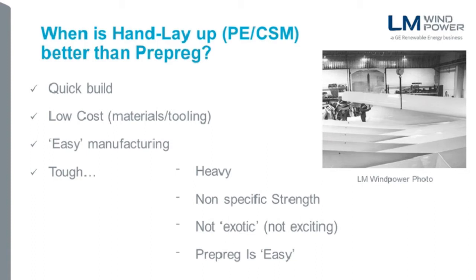So there is a place for both manufacturing processes in the engineering world. The other interesting thing for me as a process person is that when you build large boats, you get this polyester chop strand mat. You build up cured ply thickness for the shells or the hulls of the boats fairly quickly, because there's quite a lot of material, there's quite a lot of resin, and the thickness drives stiffness. So you get a very tough composite.